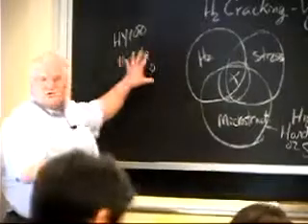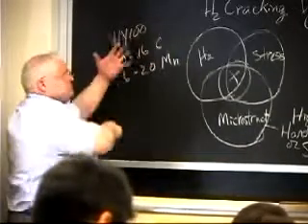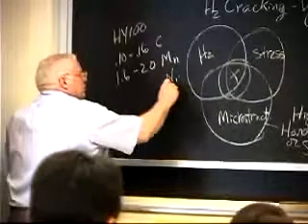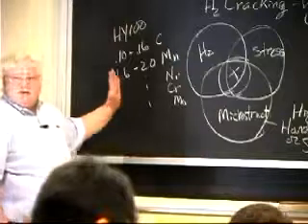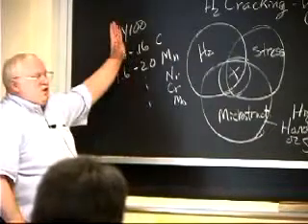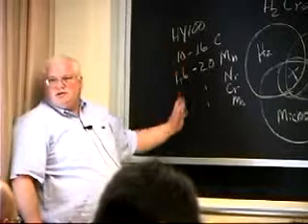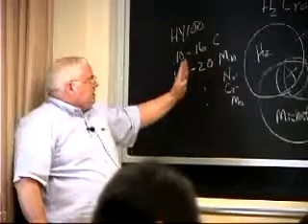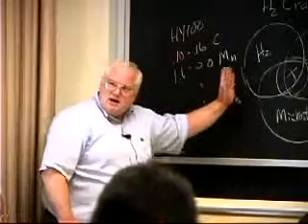I don't use these numbers, okay, but in any of these things, these are the types of ranges you would have for your chemical composition. And then you have nickel, and chrome, and moly, and all these things. Well, it turns out they had done a bunch of their testing and qualification procedures on some electrodes that were kind of in the middle of the range. But when they actually started welding the Seawolf submarine, they happened to get a heat of wire that was on the high side of the range.